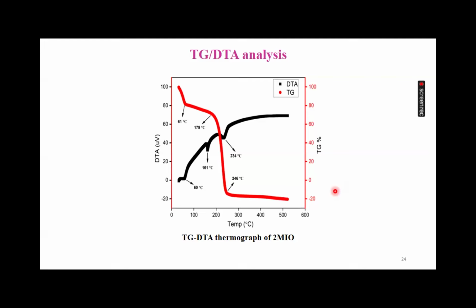TG-DTA analysis. The DTA plot curve suggests that the 2MIO compound has an excellent crystallinity as well as purity. The mass change concerning the temperature range of 60 degrees Celsius is evident, such that there are no water molecules present, which was used as a solvent while crystallization was in progress, as found in DTA.